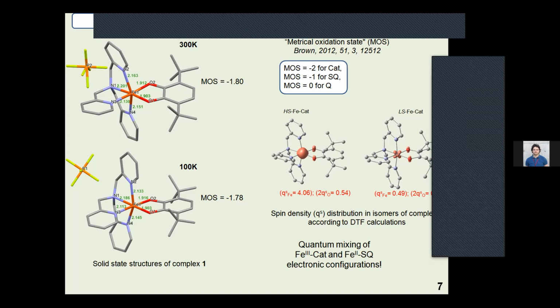DFT calculations are in good agreement with this assumption. Part of the spin density from the ferric ion is delocalized over neighboring oxygen atoms. It's caused by the mixing of some close in energy catechol and d metal orbitals.